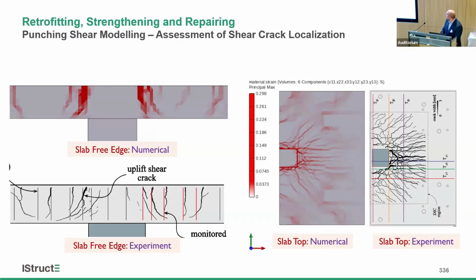Punching shear capacity is governed by something known as shear crack localization, which in simple terms is the stability of shear cracks which precede the failure. The nonlinear analysis is able to model the progression of these shear cracks before they become unstable, and these are monitored as part of the analysis to estimate the shear capacity. Throughout the analysis, throughout each time step, the dominant shear crack will be monitored, and any abrupt increase in its opening will be identified as a potential instability of the shear crack.